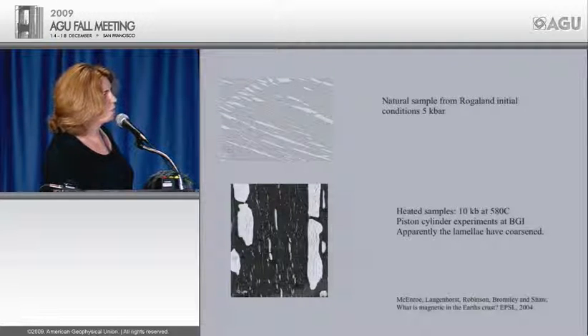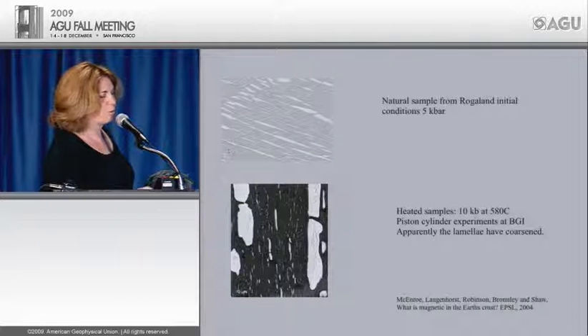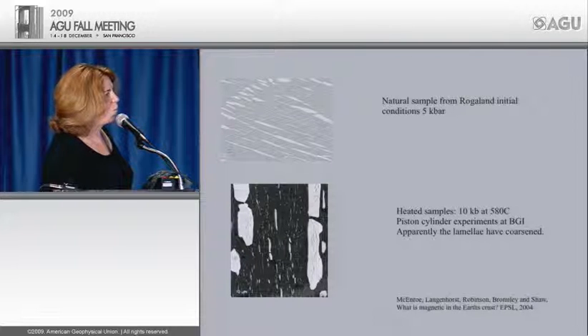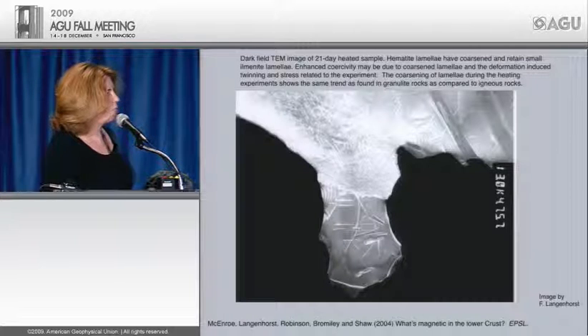So we did a series of experiments where we went to 580 degrees, 10 kilobars, and we left the samples first for about a week and then 21 days, and that was nearly a month. And what we found is basically the lamellae started to coarsen. They weren't reabsorbed. We had the hematite component and the ilmenite was being reabsorbed, and it appeared that the hematite lamellae themselves were coarsening up. We were never really satisfied that we got to the bottom of that answer. We did a lot of detailed chemical work.